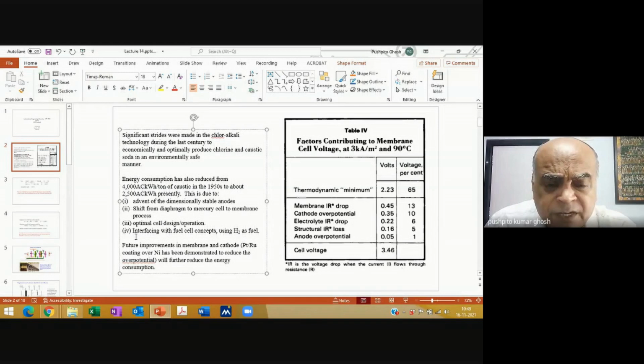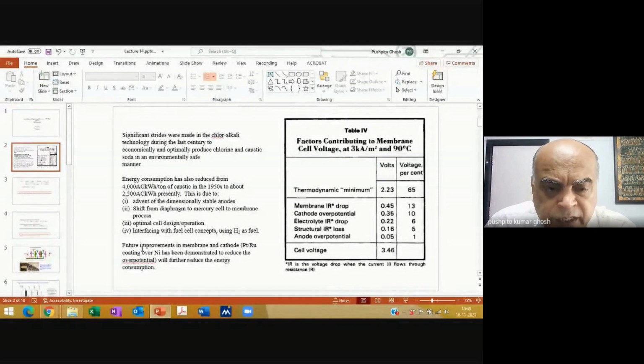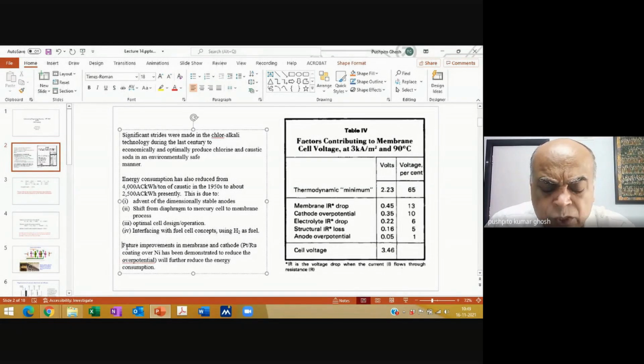And another is that, and we'll discuss this, there were certain integrations with fuel cell concepts, and so I'll talk about that. Another very important thing was that just like the anode was made dimensionally stable, we saw that the nickel catalyst is now used as the cathode. But even there, what people found is that if you can give a fine coating of platinum ruthenium over the nickel, the overpotential reduces even further. So this is something which is being looked at. I think that everybody has not implemented it. If you see the article I sent, I think it was Johnson Matthey's article, you'll find a mention of this.